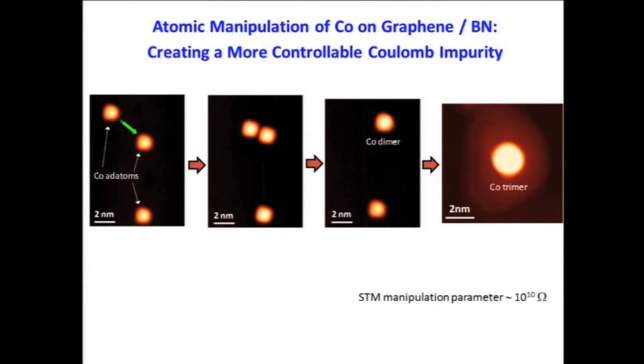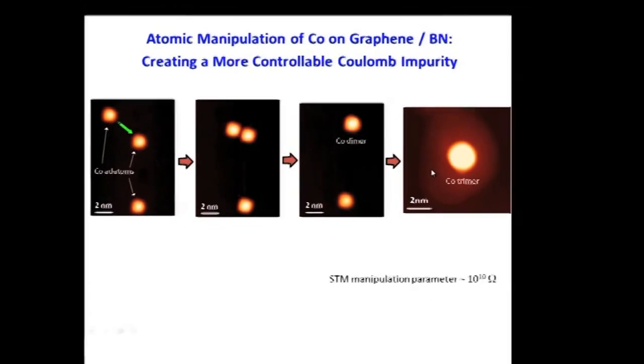For example, before we were limited to, say, monomers, the cobalt monomers, but now we can take the cobalt monomers and move them together. You can see these three have been moved together like that. Then these two we move together with the STM tip to create a dimer. And then we can move this one over here to create a trimer. So now we can create these small clusters which have different charging properties. And that's actually been good for us, because when we look at this cobalt trimer, for example, we find that these clusters have much nicer charging properties than the monomers. And we can put them into stable charge states.